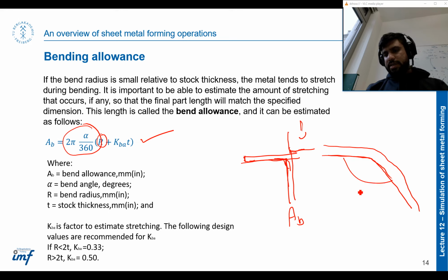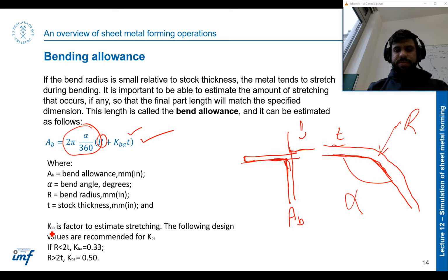So one is this angle alpha, which is given here, and the other is this radius of bending. And then of course we have our thickness of the sheet, and then there is a constant factor to estimate stretching. Now, generally the following design values are recommended. If the radius is less than 2 times thickness, this value of kb is used, and if the radius is greater than or equal to 2 times of the thickness, then we use this value. And from this formula we calculate the bending allowance.